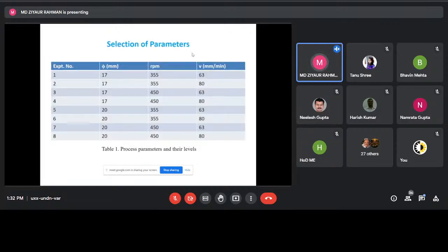The following parameters were taken. We had two levels of shoulder diameter, 17 millimeter and 20 millimeter. Two levels of tool rotational speed, 355 RPM and 450 RPM. And two levels of traverse speed, 63 millimeter per minute and 80 millimeter per minute. And this is the design of experiment according to Taguchi L8 orthogonal array.